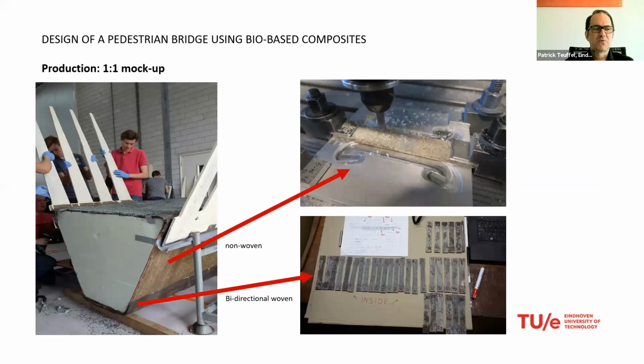Here you can see the production process on the left side. It's a 1-to-1 scale mock-up. So the green grayish internal stuff, that's the PLA core, which was used as the lost formwork, and the shell structure around it, that's the bio-based composite material, which is a combination of non-woven and bidirectional woven material, as well as unidirectional materials in the areas where the stresses are the highest.